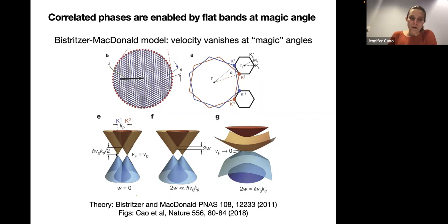And so if these Dirac cones don't talk to each other at all, then they're separated in momentum space by some distance, which is determined by the twist angle, and they'll cross at some energy, which is determined by the twist angle and their velocity. But there's nothing that stops them from hybridizing. And so generically, there'll be some interlayer tunneling strength, and that will cause a gap to open when these Dirac cones hybridize. And when that interlayer tunneling strength exactly matches the twist angle, then you'll get this very special point where the Dirac cone velocity vanishes and you have this flat band which is occurring between the two Dirac cones. And that's referred to as the magic angle.